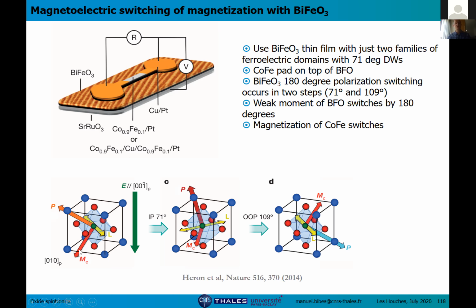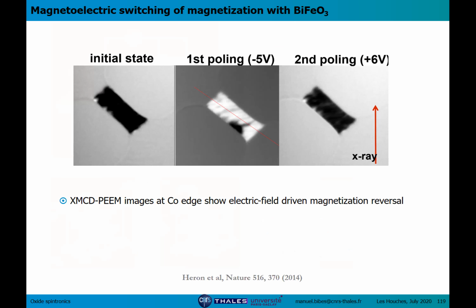Okay, so basically you want to go from here to there. So you switch the magnetization direction. This is not a very simple process. It occurs in 2 steps, but it seemed to work actually, at least in this kind of samples. So this switching works, and you can see that here. This is X-ray photoemission electron microscopy, XPEEM, at the cobalt edge, looking at the magnetic domain structure of the cobalt iron layer when a voltage is applied to the bismuth ferrite.